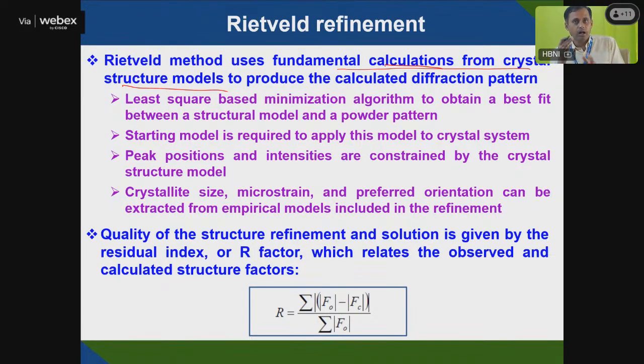You can find out how much it deviates. It is based on a least-squares minimization method. So you need a starting model to begin. In the currently available software, like FullProf or something, you can get a starting model. You choose your model, and by using that model, you can analyze all those parameters. You can get crystal structure, microstrain, preferred orientation, peak position, intensity, everything from the Rietveld